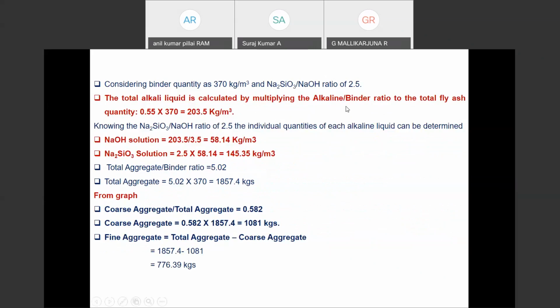Here, first I had selected the total fly ash quantity, 0.55 into 370. We are going to get the alkaline content. From that alkaline content, I know sodium silicate to sodium hydroxide ratio as 2.5. From this, we are going to get the sodium hydroxide and sodium silicate. Once you know the total aggregate to binder content, already the binder content you know as 370, so that you are going to get the total aggregate.